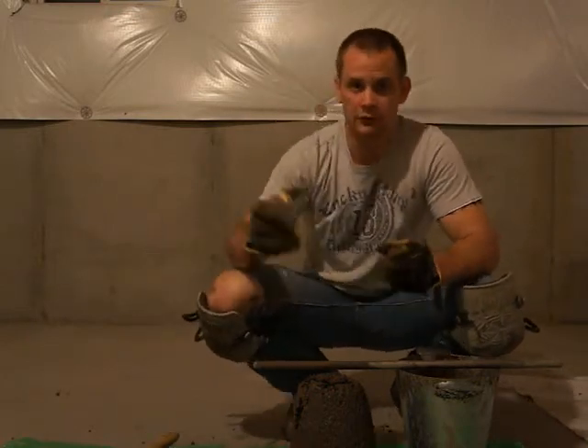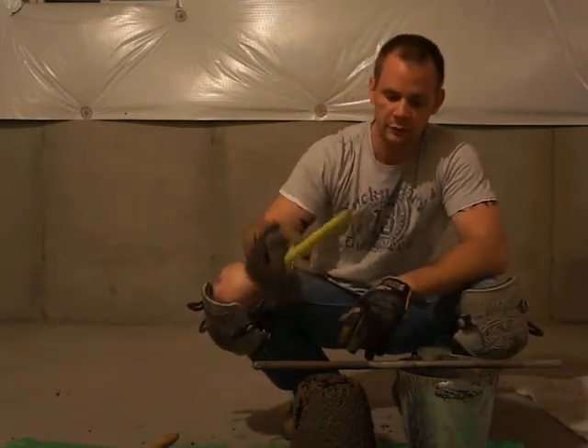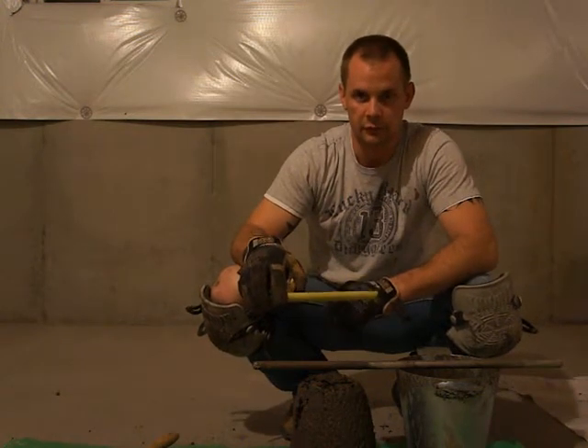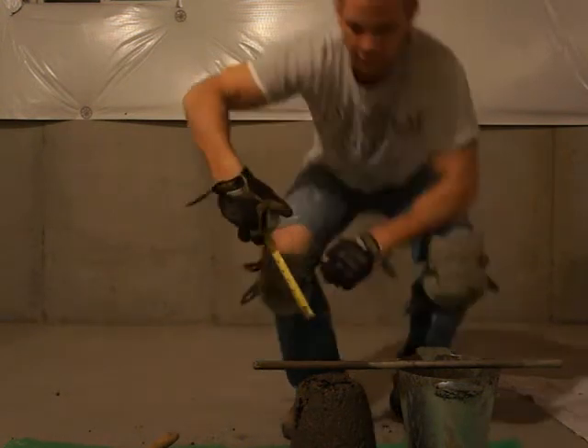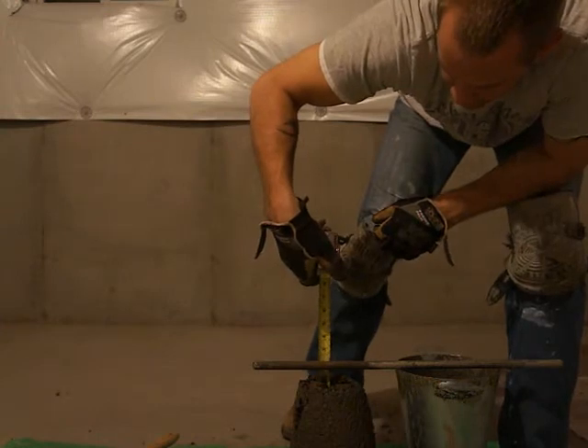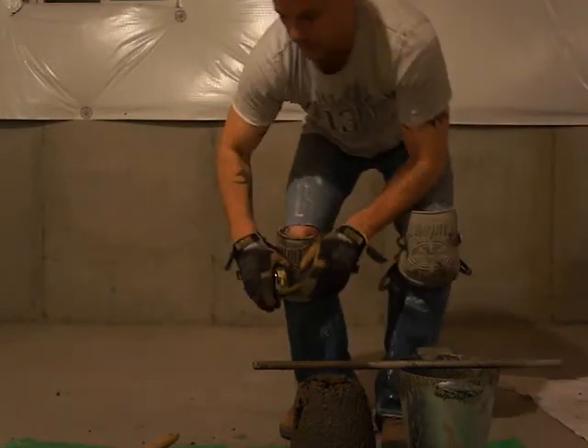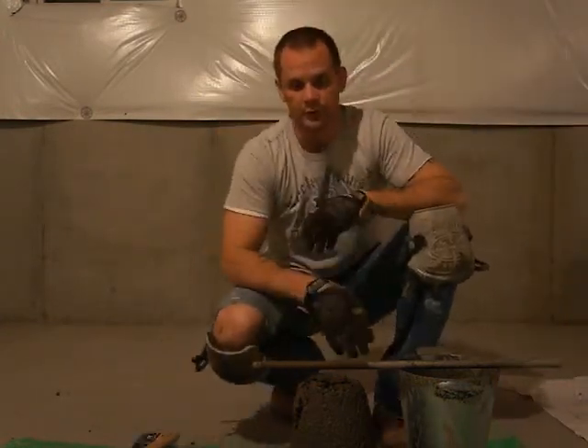So what we're measuring for is the distance between the bottom of the rod and the top of the test specimen. In this instance, it is right about 2 inches. So this is what would be called a 2-inch slump.